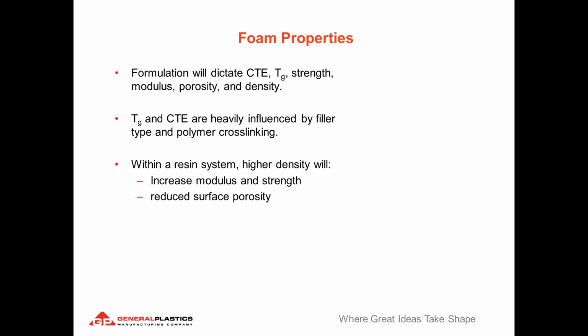So within a resin system, higher densities will both increase modulus and strength and also reduce surface porosity. Of course, one thing I didn't list on there is the obvious one, that as you are increasing your density per cubic foot, the cost also goes up. So that's also where you get into surface finish requirements. If you desire a very fine surface finish, but you have a very large tool, perhaps you would like to use a lower density material and then use a filler and sealer system to create your fine surface finish. Those are all things to discuss with your supplier to make sure that when you order a foam material, that it shows up as you expect.